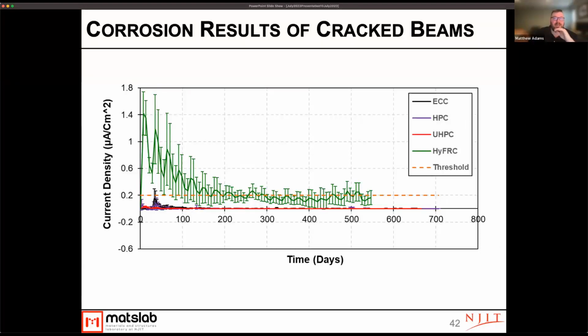What we see here is above that red line typically means that corrosion may have occurred. So that dashed red line, if our corrosion current density is above that, that means that corrosion is likely to have started. The only system that we started to see corrosion in our cracked beams out to 700 days was the HyFRC system. We actually had to stop that test just after 500 days. But we did see that corrosion was likely to have started in the HyFRC system. But even our HPC system, the normal concrete, which is a standard mix used by the New Jersey DOT, is performing quite well in terms of corrosion performance.